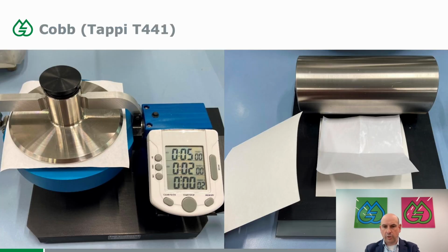Just to remind everybody, how is it done? You've got a COBB tester here. You use that in different durations. So you put the paper into it, you've got water in the bucket underneath, you flip it over, and then the water will sit on top of the paper for a certain number of minutes, and that's given in seconds. So a COBB 300 is 5 minutes, a COBB 1800 is half an hour, and then later on you dry off the excess water, and then you weigh the paper and you check the water absorption.